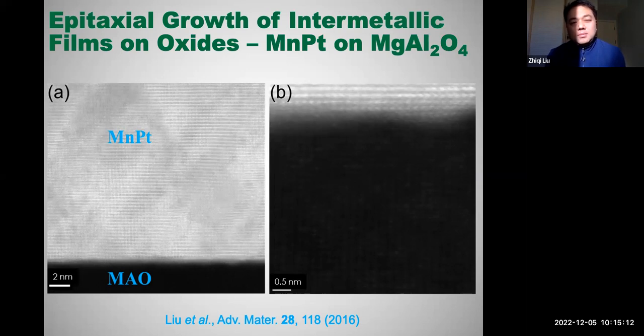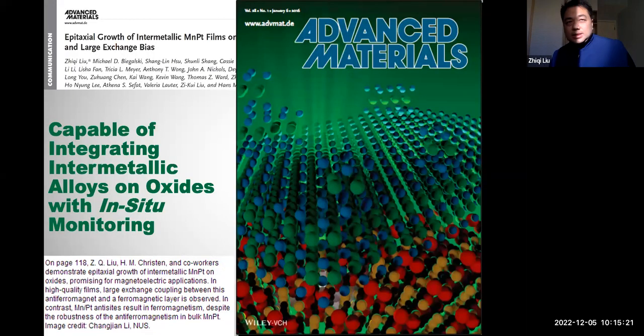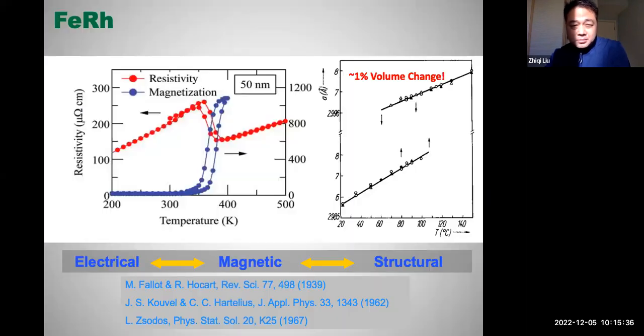Sorry, this MnPt is an antiferromagnetic metal. So with certain optimization and also with this sputtering, we can try to grow high quality magnetic thin films, especially magnetic metals, onto oxide. And then we can try to test our previous idea, whether we can try to use the piezoelectric strain to effectively control the magnetization of a ferromagnetic metal or an antiferromagnetic metal.